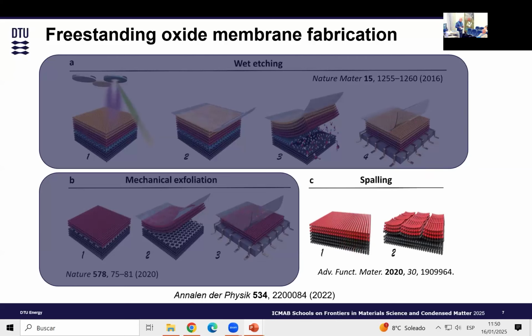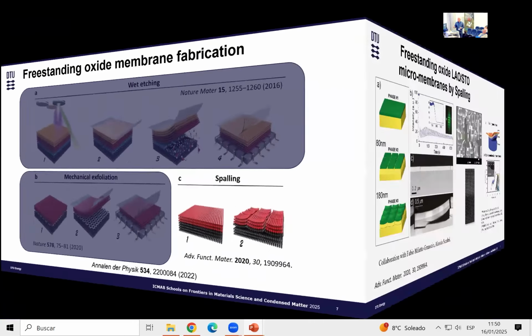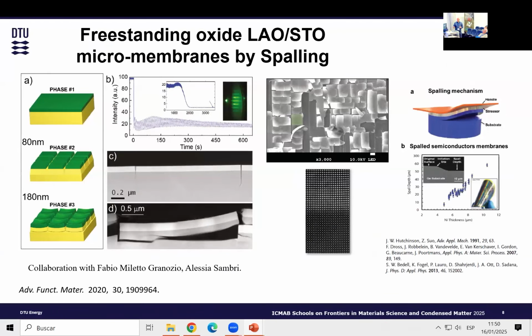So what is spalling? Spalling is what happens when you grow normal epitaxial material and, after a certain thickness, the strain that forms in the material causes it to delaminate from the substrate, and it forms flakes. This work was initiated by Fabio Miletto Granozio, and we followed it together with him.